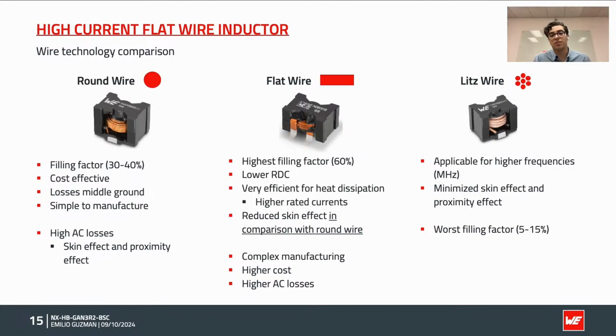Now, because of the flat wire, it's more complex to manufacture, and thus it increases the cost. And it also has higher AC losses in comparison to the litz wire. Now, for the litz wire, it is more applicable for higher frequencies in the megahertz range, and it has a minimized skin effect and proximity effect due to its packing method, although it has the worst filling factor between the three, from 5 to 15%.